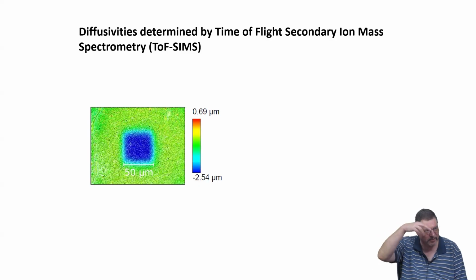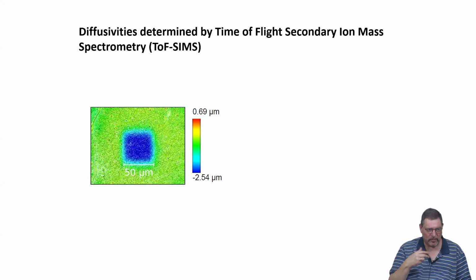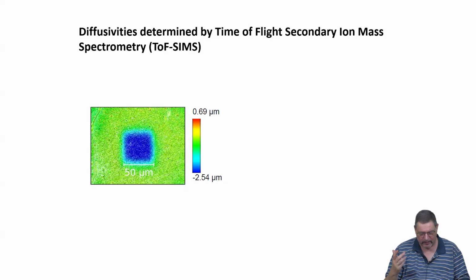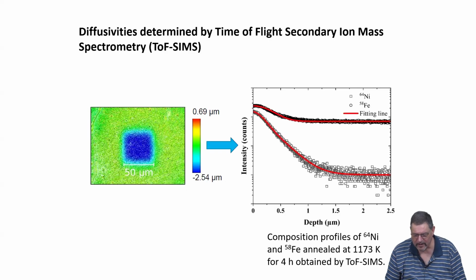Yeah, and then basically you sputter a crater, right? And then you do it continuously, so the crater gets deeper and deeper and deeper, and you collect information about how many of this specific isotope is present at each specific depth. Normally you would measure just as a function of time, and then you have to recalibrate your measurement afterwards by measuring the sputter crater depth at the maximum time. And then you assume that time and crater depth vary linearly with each other, so you have linear dependence on each other. Then when you do this, you get again a diffusion profile.